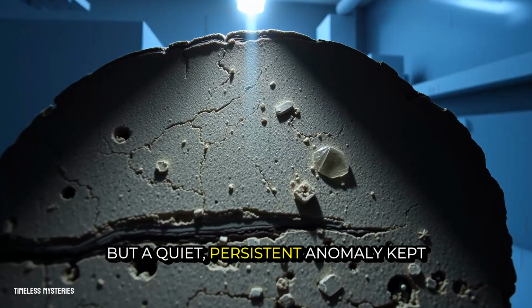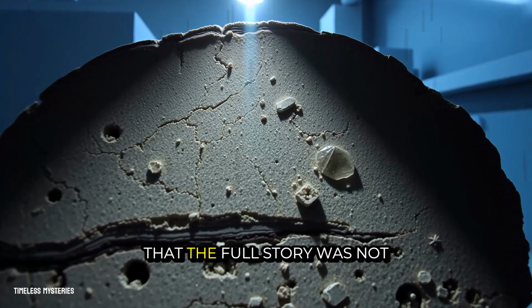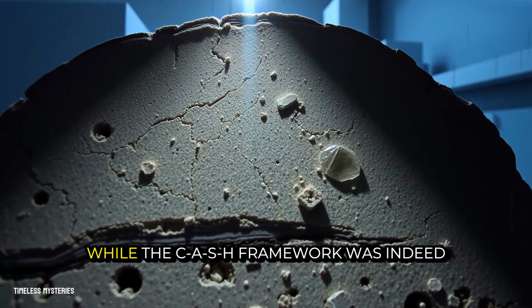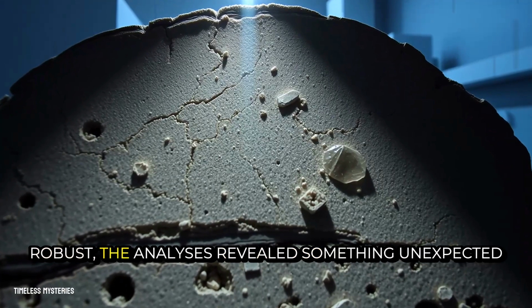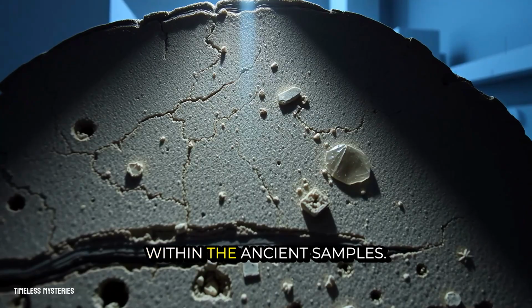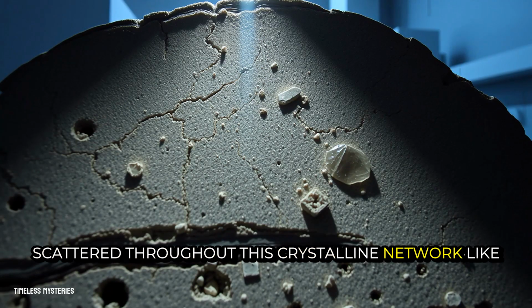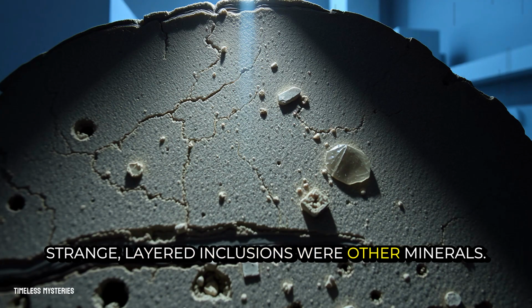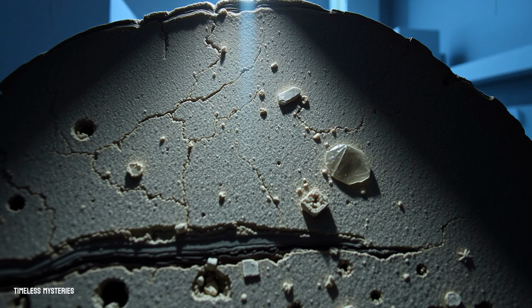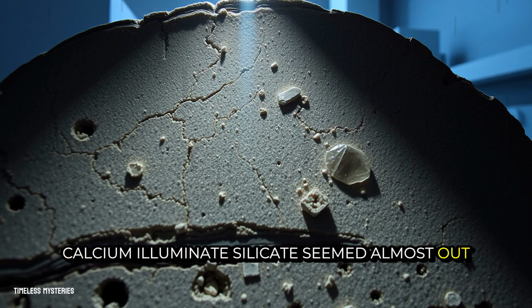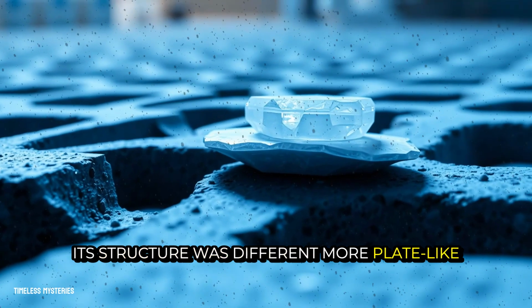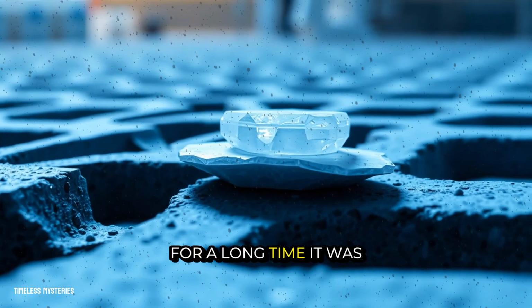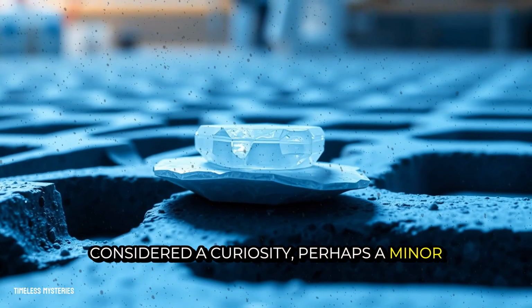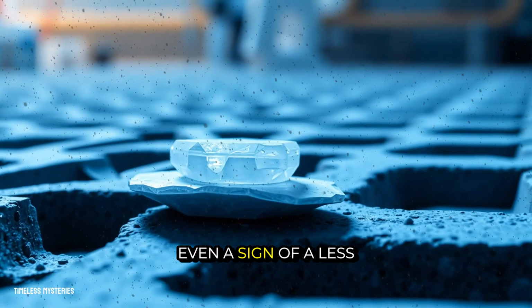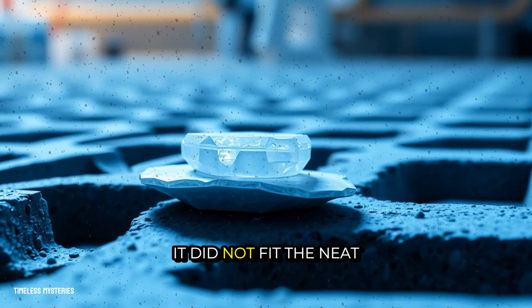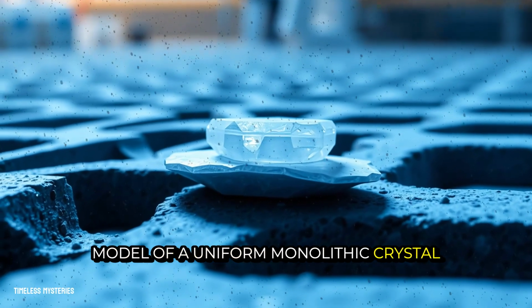But a quiet, persistent anomaly kept appearing in the data, a clue that the full story was not yet on the table. While the CaSH framework was indeed robust, the analyses revealed something unexpected within the ancient samples. Scattered throughout this crystalline network, like strange, layered inclusions, were other minerals. One in particular, a form of calcium aluminate silicate, seemed almost out of place. Its structure was different, more plate-like and less interlocking. For a long time, it was considered a curiosity, perhaps a minor byproduct of the initial mix, or even a sign of a less-than-perfect reaction. It did not fit the neat model of a uniform, monolithic crystal structure.